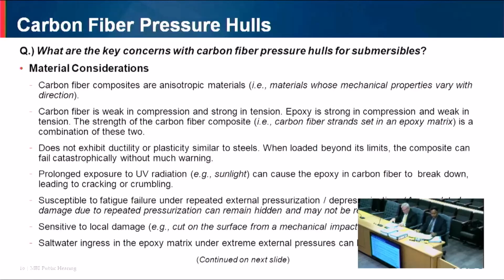So the next thing is carbon fiber composites are notch sensitive. They are sensitive to local damage. So if you have a cut on the surface from a mechanical impact, this can grow to form a crack, which can lead to failure of the pressure hull. Okay, so it's very important to protect carbon fiber composite pressure hulls from impact loads. Okay, and then saltwater ingress in the epoxy matrix under extreme pressures can lead to delamination.